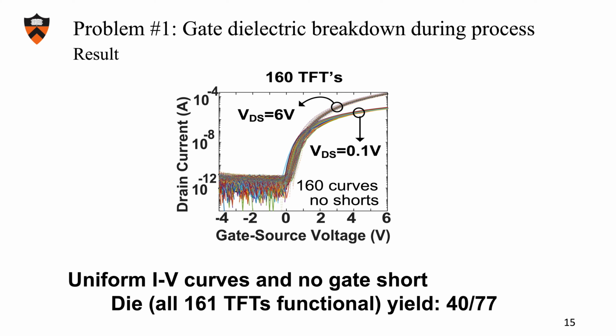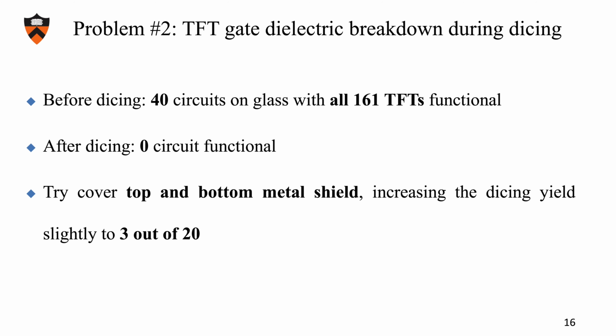That's the first problem. Another problem is gate dielectric breakdown during dicing. We can see that before dicing, there are 40 circuits with all 161 TFTs functional per circuit on glass. But after dicing, no functional circuit is left. We also tried to cover the sample with top and bottom metal shields, but this only increases dicing yield slightly to 3 out of 20.